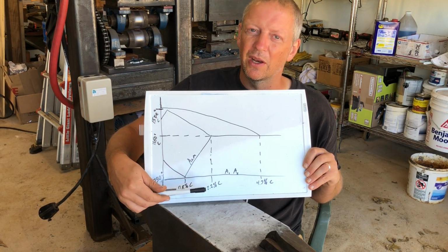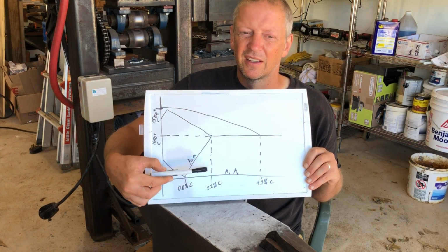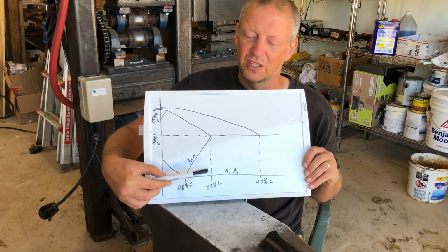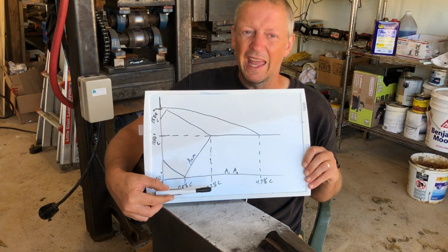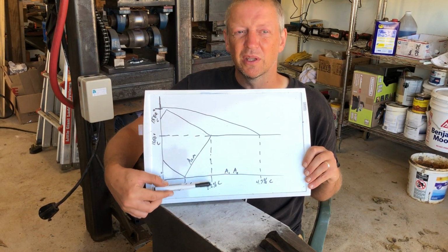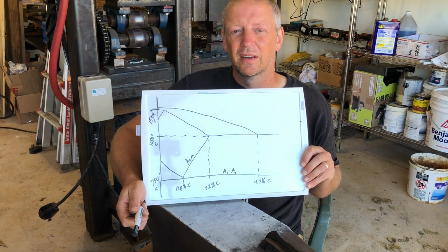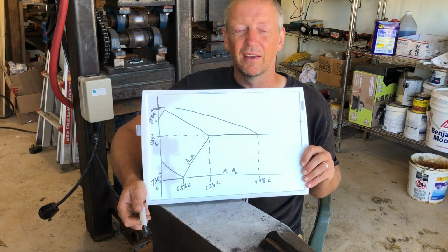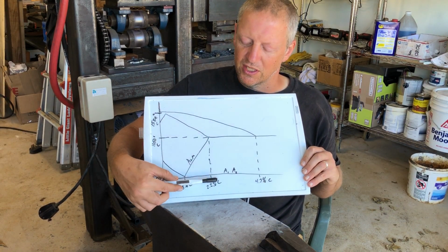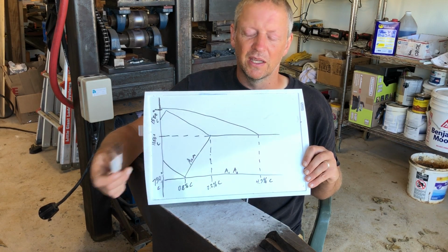So on the way up, you may notice it visually as, I guess I would say, a sort of stickiness of the color. You're heating and you find that the edge comes up to temperature and begins glowing really easily, but there are some sections in there that are just not apparently coming up to temp as fast as you would expect. What you're seeing is that pause as it is making the transformation.